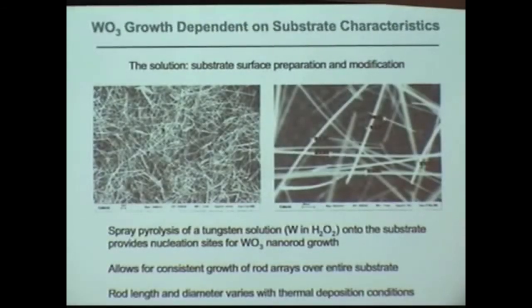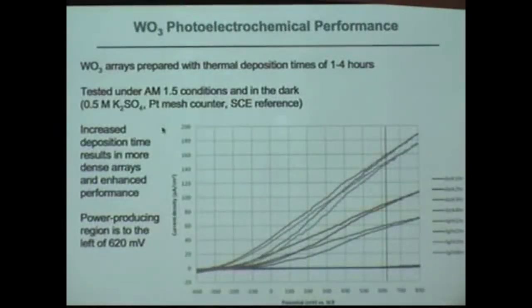They're not oriented and felt yet. We just grew them by vapor phase synthesis to show we can get them photoactive in this form. Again, it's the nanostructured idea. Diffusion lengths are too short to make bulk materials work very well, but we just confine the geometry radially to make sure we can get them all sideways. They work. 800 millivolts open circuit voltage. So that's the N-type photoanode.